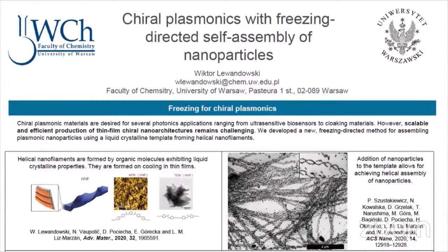And we successfully achieved that by doping the chiral plasmonic systems in the isotropic phase with a small amount of chiral low molecular weight compounds. This way, we achieved the ability to control handedness, the chiral response of the materials at the bulk scale, but also we have shown that there are several types of nanoparticles that are compatible with our systems, and thus we can control the spectral range. Chiral plasmonic films are tremendously